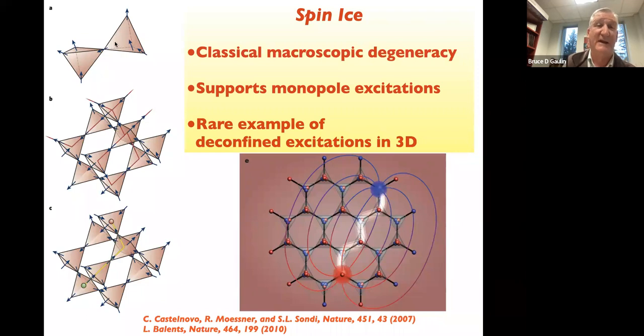And the interesting thing is that once that excitation has been formed, once the energy has been put in to flip the spin, then those 2 defects can actually drift away from each other. And this picture in the lower right-hand corner is indicating 2 of these defects having drifted away from each other. They can separate to either end of the crystal. But once separated, they behave like the monopoles that make up a magnetic dipole. Okay, so they interact with each other via some sort of Coulomb interaction.